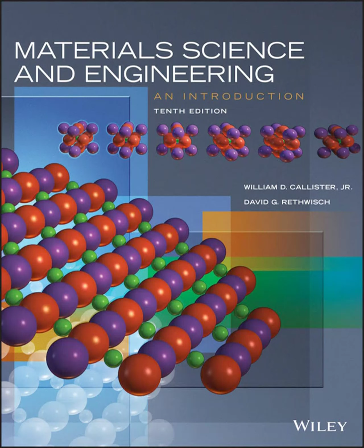They're too big to fit in the gaps. And what really stands out is that interstitial diffusion is usually much, much faster than vacancy diffusion. Why is that? Well, two main reasons. The atoms doing the jumping are smaller and just more mobile. And crucially, there are generally way more empty interstitial positions available for them to jump into compared to the number of vacancies, so more pathways open.